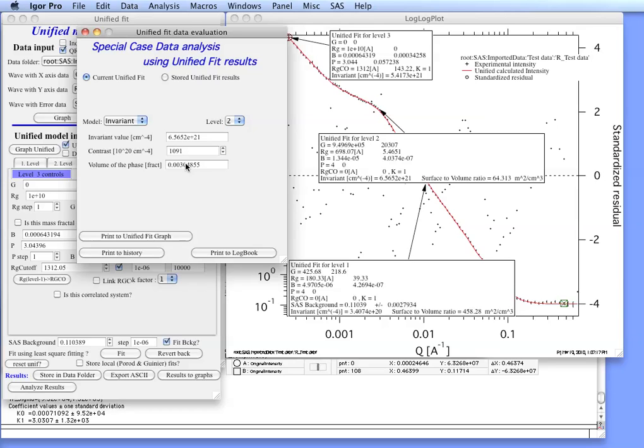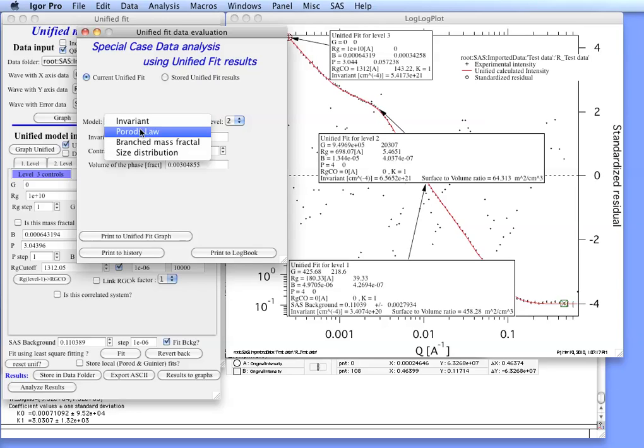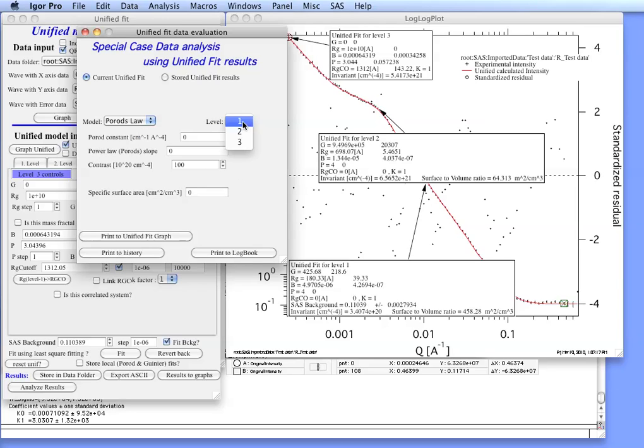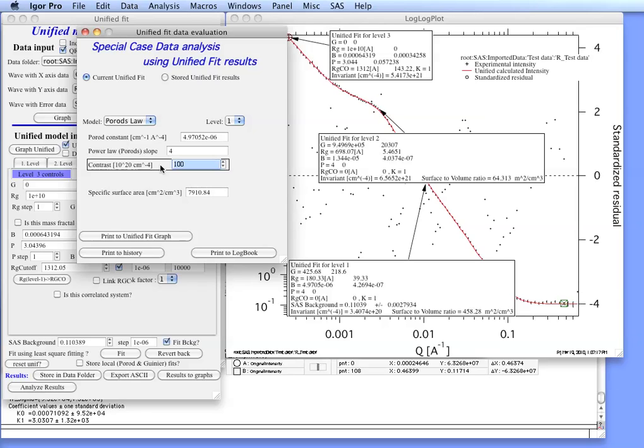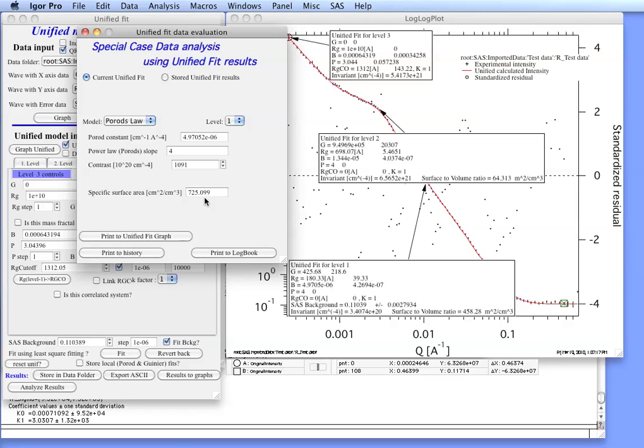The other thing which you can analyze is Porod's law. If your Porod's slope is 4, then the B is actually Porod's constant. So that number is Porod's constant and P is 4. And if you have the proper contrast, then the tool will calculate for you specific surface area in cm² per cm³. Again, this depends on the absolute calibration of your intensity. The surface to volume ratio does not, but the specific surface area does.